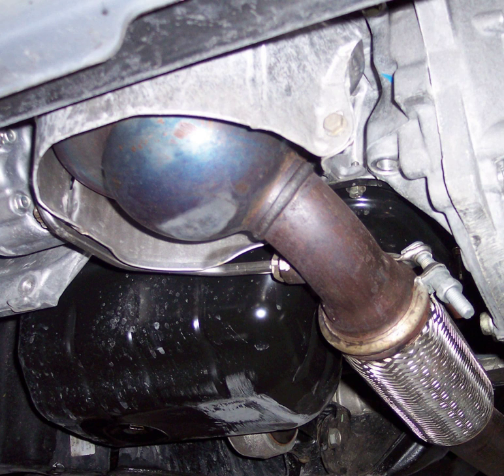This is mostly an issue if the filter has become loaded more heavily than usual, and is more of an issue with passive systems than with active systems, unless there is a system breakdown. Cordierite filter cores look like catalytic converter cores that have had alternate channels plugged; the plugs force the exhaust gas flow through the wall and the particulate collects on the inlet face.